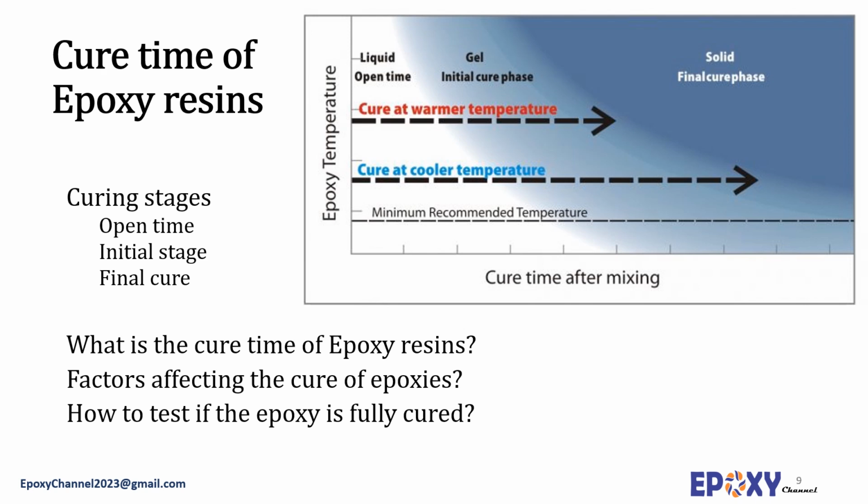The general rule of thumb is that for every 10 centigrade increase in temperature, the cure time is cut in half. An undercured component will still feel slightly sticky or gummy, while a well-cured part will feel smooth and hard. A useful way to look at the cured epoxy is to carry out a differential scanning calorimetry, or DSC. DSC measures the energy input or output of the solid resin as it is scanned from low to high temperatures.